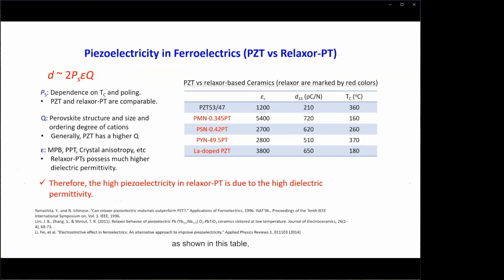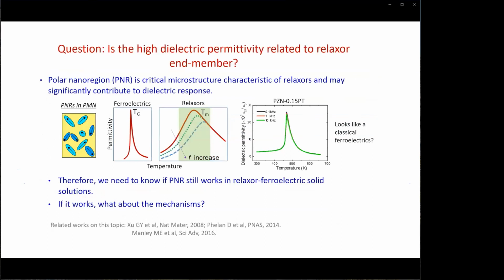As shown in this table, we can see that Relaxor-based ceramics show much higher dielectric permittivity. Here, Relaxor piezoelectrics are marked by red colors, and the compositions of all these ceramics are around the morphotropic phase boundary. So the first question is: does Relaxor behavior lead to high dielectric permittivity in Relaxor piezoelectric solid solutions?